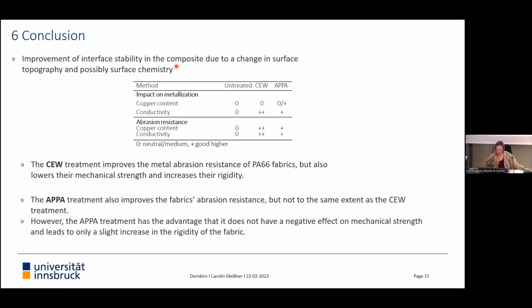The plasma also improves the fabric's abrasion resistance, but not to the same extent as the CEW treatment. But the plasma treatment has the advantage that it has no negative effect on the mechanical strength. And with this slide, I come to the end.